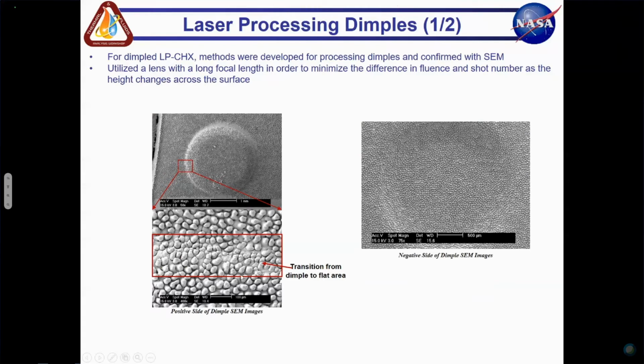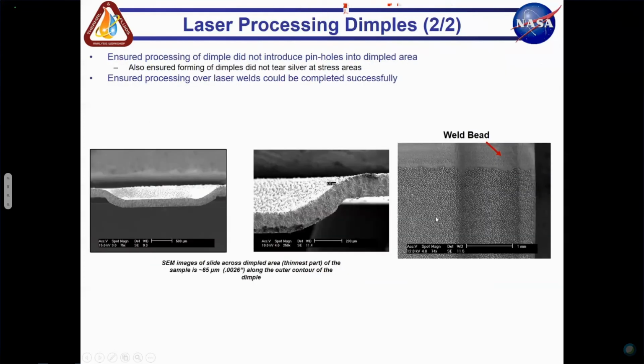I've got some pictures on the next couple of slides to verify how our laser processing was going. So this is all the dual pulse. This is a dimple that was formed in that silver sheet. You can see we're getting pretty good patterning over our surfaces. This is a zoomed in picture in the bottom left-hand corner of the transition between a flat plate and up through the dimple. And we're getting good microstructures on that surface.